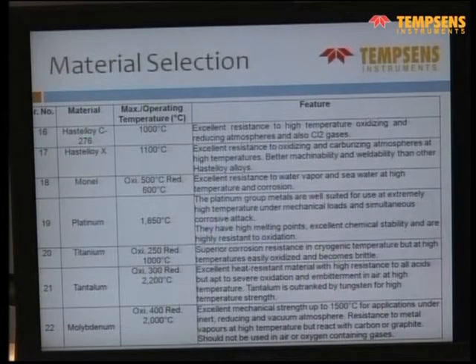Then platinum we are using a lot in glass temperature sensors. In case of molten glass, there is no element which can withstand that kind of aggressive nature, and platinum is a material which is non-wetting for molten glass. So the molten glass is not sticking to platinum. So we are using platinum thermowells for such cases. Similarly, titanium for some chemical processes we are using. Titanium sheets we are using. Then tantalum is for reducing atmosphere at high temperature, and tantalum is for inert or vacuum application, and molybdenum we are using for reducing atmosphere or inert atmosphere. So all these kinds of thermowells are possible. We also supplied with some special coatings on tantalum. So all these things can be offered to the customers.